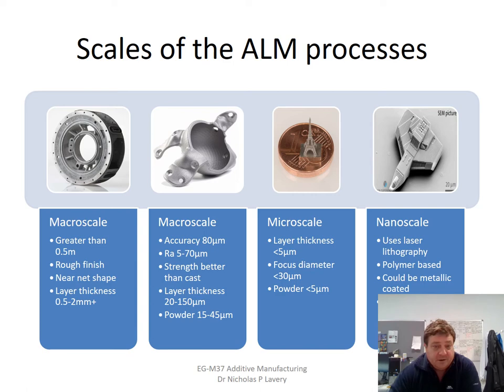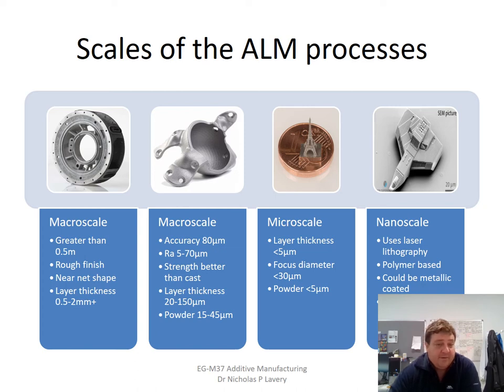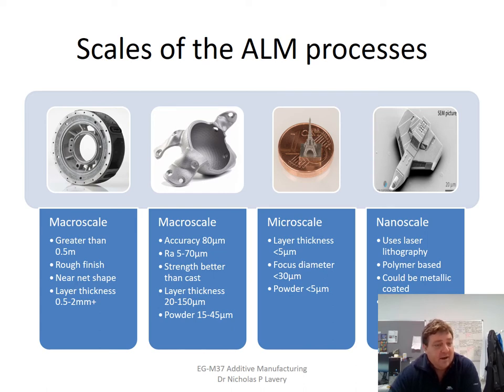The range of processes can be really wide in scale — from the large macro scale all the way down to the nanoscale. On the macro scale, you might have something like wire arc additive manufacturing, electron beam melting, or some large powder bed systems that work with metals. Even polymer systems like the Objet1000 have a one-meter scale build envelope. Typically for the metal-based systems at large scale, this comes with a relatively rough finish and near net shape, so you'd have some machining afterwards. Layer thicknesses can be much larger, allowing parts to be built in relatively fast times.